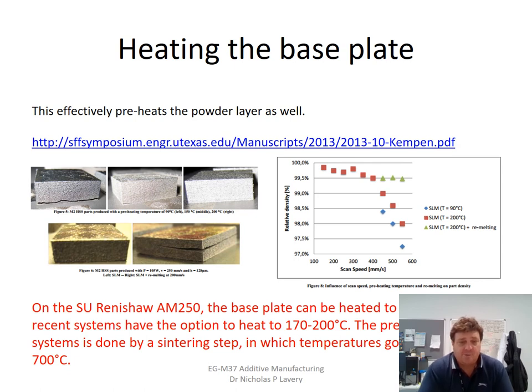So one of the other parameters that we will change is the base plate temperature. That'll be heated, and there's a paper by Kempen 2013 on the effects of preheating the base plate. This shows that particularly for higher scan speeds, you're able to get higher densities when you've preheated the base plate. They've gone up to 200 degrees. Our base plates go up to only 170 degrees. But you can avoid cracking and various in-situ process-based defects by preheating.